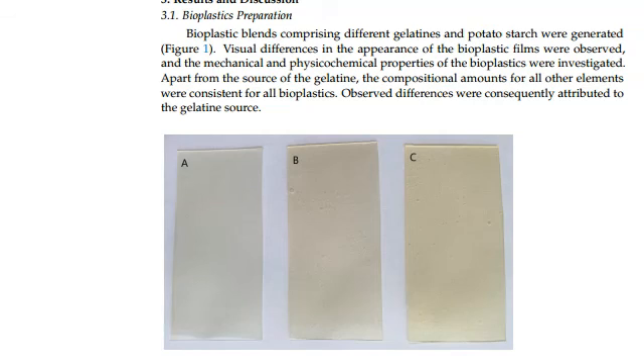Bioplastics made with fish skin gelatin lost significantly less weight compared to the bioplastics made with porcine or bovine gelatin. Increased starch concentration resulted in increased solubility. There was no statistical difference between the moisture content in any of the synthesized bioplastics.